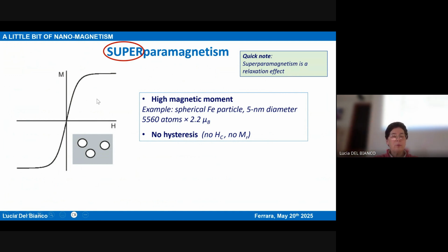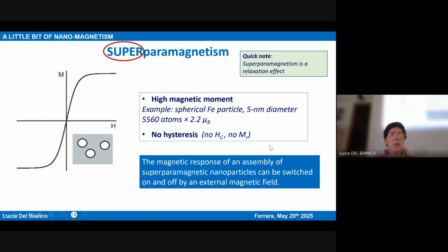But when you decrease the field to zero, you won't observe any longer the phenomenon of magnetic hysteresis. So no coercivity, no remanence. And so in short, this means that if you have an assembly of superparamagnetic nanoparticles and you apply a field, you have a high magnetic response. But if you decrease the field, the magnetic response goes to zero. Namely, you can switch on and off the magnetic response by switching on and off the magnetic field. And obviously, this can be quite interesting if you want to make a magnetoresponsive material.